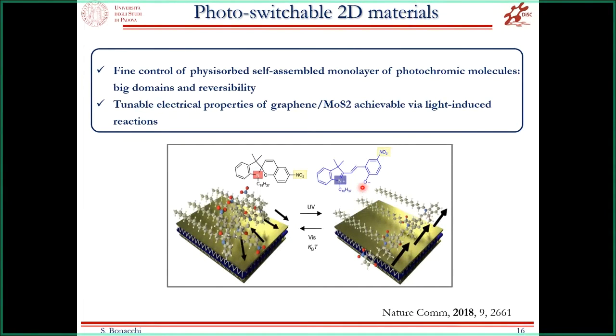So with this approach, we were able to show the possibility to play with the same simple molecule and with a supramolecular approach, first to create a higher order assembled molecule, and then to induce different kinds of dipole moment on top of graphene, and then induce a strong effect on the electrical properties of a 2D material. And this result was true not only for graphene, but also for different kinds of van der Waals heterostructure